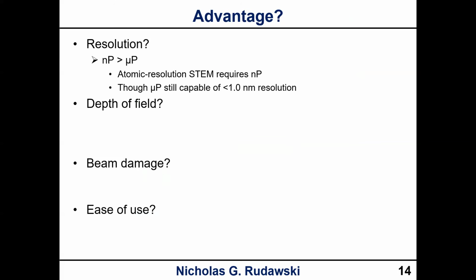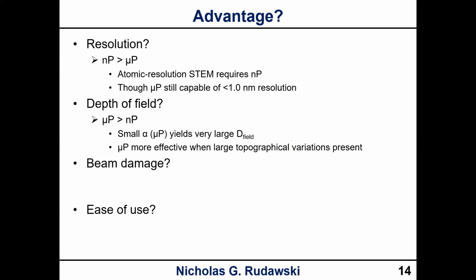Okay, so resolution, obviously nanoprobe is better. If you want atomic resolution, you need to do this in nanoprobe, but we did see with that table that microprobe can still get, in principle, sub-nanometer. Depth of field, microprobe has a big advantage here because you have a small alpha. So the implication is when you have large topographical variation, microprobe is going to be advantageous.